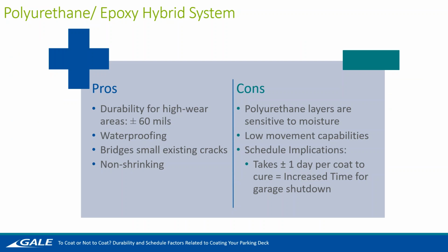Durability for high wear areas. It's a thicker system than the polyurethane. You can increase the thickness as well if you need a super durable coating. It's waterproofing. It also can bridge small existing cracks. So a 1/16 of an inch crack, you don't have to repair, you can just coat right over it. And it's also non-shrinking.